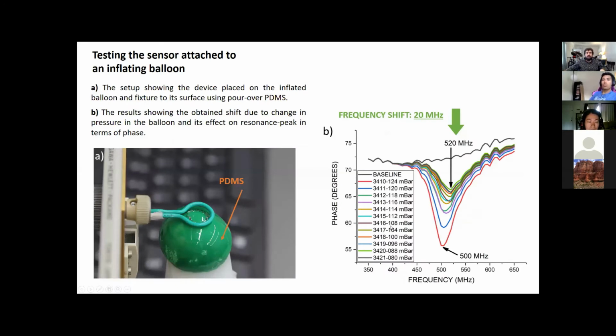Once I made the devices, the first way I tested them was literally attaching them to a balloon, like a birthday balloon. I put the device on it, and using PDMS, which worked like a glue, I completely attached the device, and I read a really nice shift of the resonance frequency, which is this point, to the left. So the larger the device got, the lower the resonance frequency was, and that was super encouraging, showing that the sensor itself works as we expected.